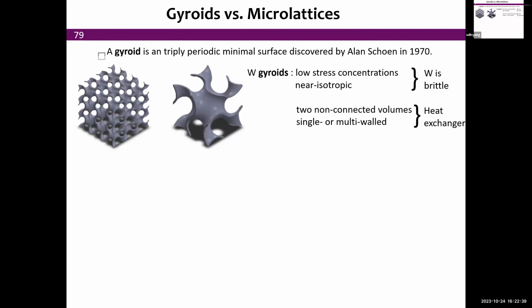Now, with the few minutes I have, I just want to show you, again, with tungsten, which is the most difficult material to work with, that we can go well beyond just those simple lattices. We can create so-called gyroid structures, which if you see are 3D structures, load-bearing, but without stress concentration at contact points between lattice struts. Also, even though it's not quite easy to see, this gyroid structure separates two volumes, which are not communicating with each other. So it can be used for a heat exchanger system that is very homogeneous. So that's just the topology of those.